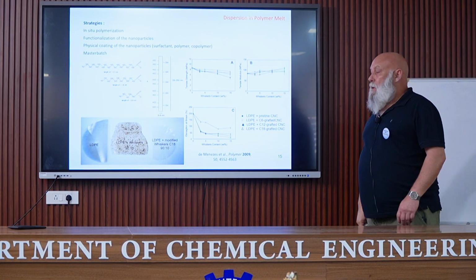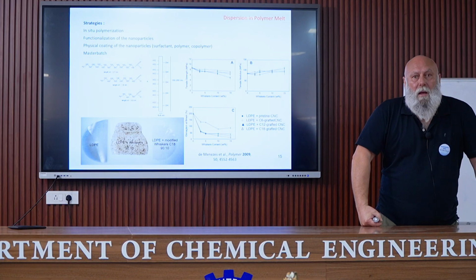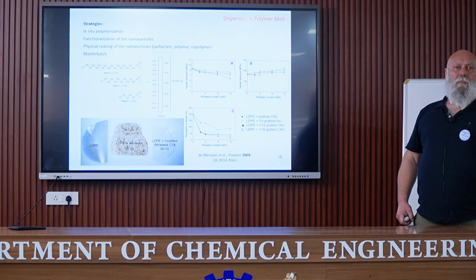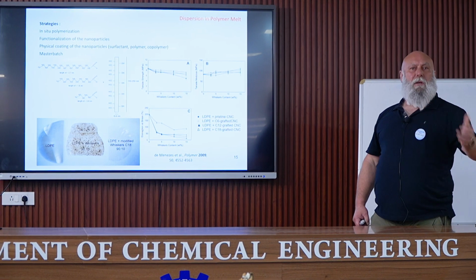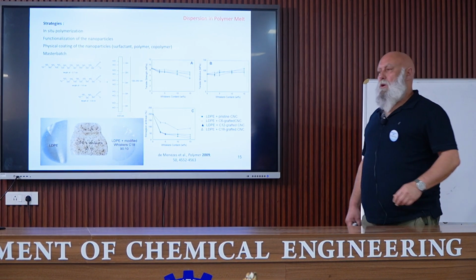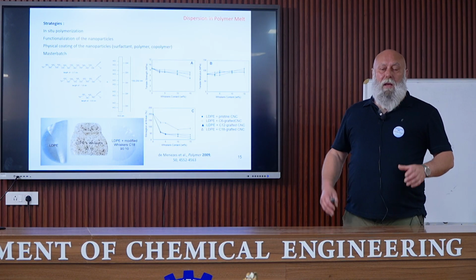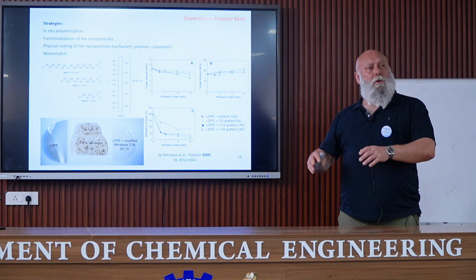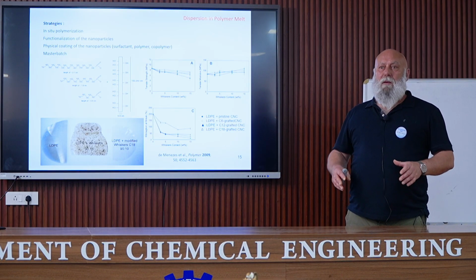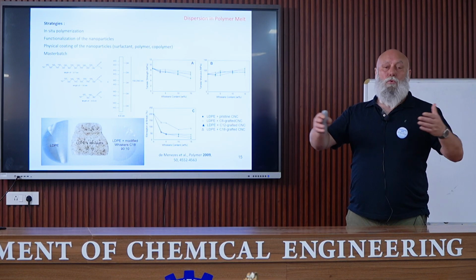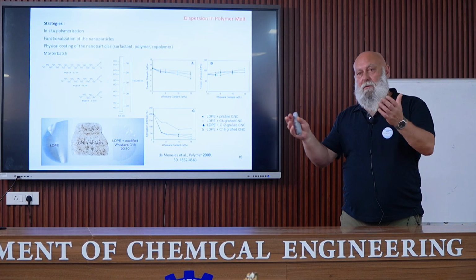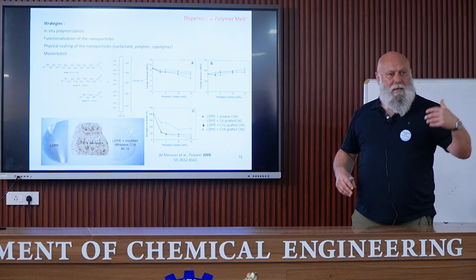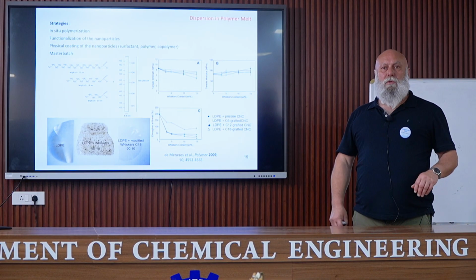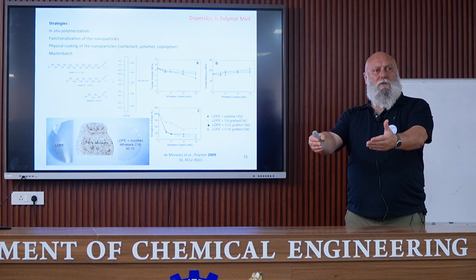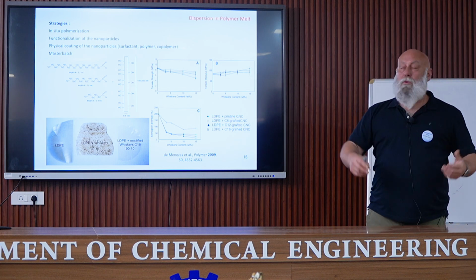Maybe I can define. Master batch consists in preparing a composite, usually by casting evaporation, with a high amount of filler. It's usually 30 or 40%. And so we have a homogeneous dispersion of the filler in the polymer, and this master batch can be extruded with virgin polymer pellets to dilute the filler, to reach, for example, 10% or 5%, depending on the amount of master batch and virgin pellets which are used. Okay, so the filler is dispersed in the matrix first at a high amount, and then it is diluted.